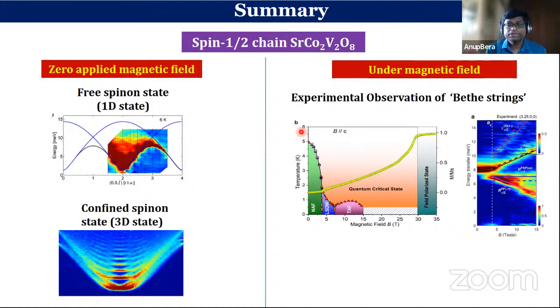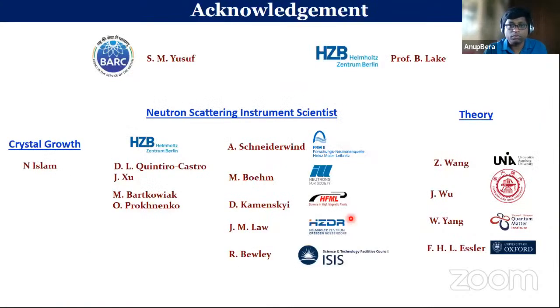And then under field, when we go to the quantum critical state, we see the presence of string states, and we experimentally proved the string states for the first time, which was not observed for a century. The prediction was made in 1931, and over the century it was not observed, and for the first time our group experimentally proved that indeed this kind of string state is present in the spin half chain compound.